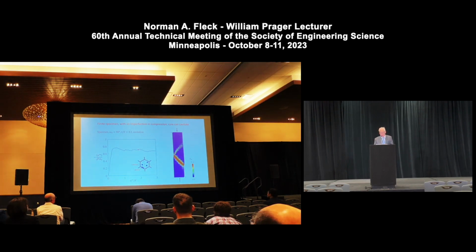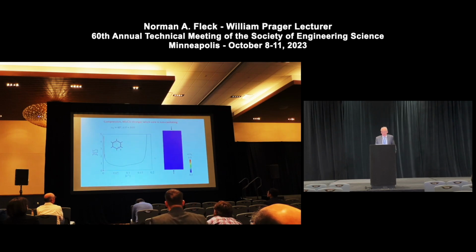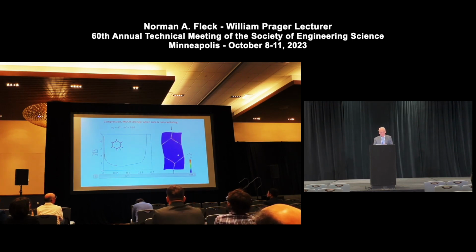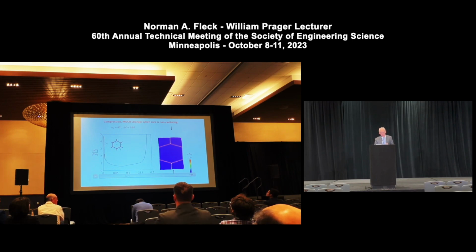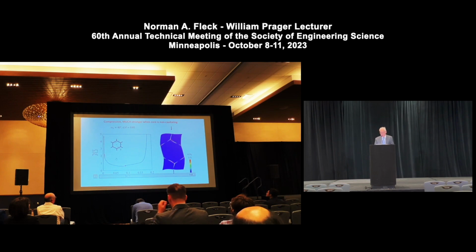If we contrast that with the case where we keep the volume of each cell constant, this is a non-cavitating case, constant volume inside, we dramatically change the response. We have initial behavior, which is stretching, gives a high peak load, but then after that, the lattice rotates into a bending mode, strong softening takes place, and one would anticipate from this periodic unit cell response, this very strong softening behavior, that you would get lots of instabilities.